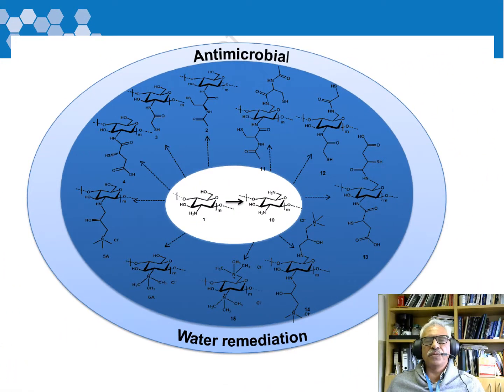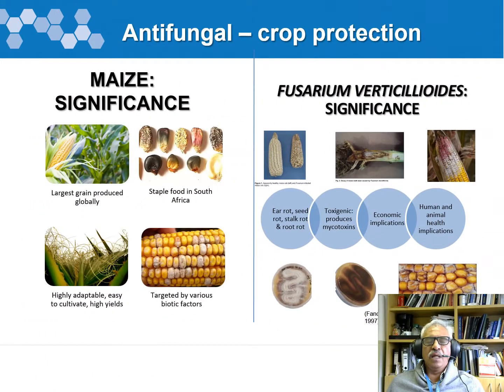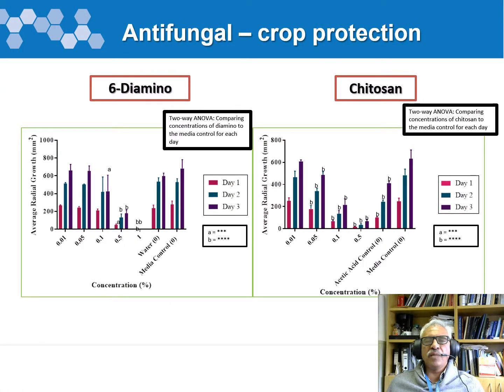So we've made quite a range of diamino derivatives which have good antimicrobial activities, and some were used as ion exchange resins for water remediation. These polymers also have a charge, so they were very good in antifungal properties, and it's currently undergoing tests to check its ability to improve crops. As you can see here, it's the diamino versus the chitosan with 0.5 and 1%. You get complete inhibition of the fungus that's responsible for rot in maize. Also this material is quite easily water soluble, whereas the chitosan is not. So this is definitely a big step towards making commercially available material.